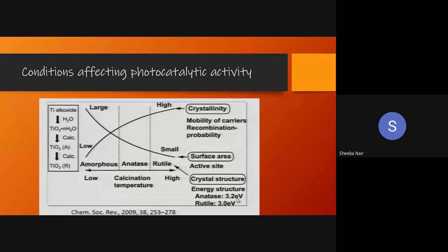Okay, what happens to crystallinity? The crystallinity improves, is high when you go from the lower to higher calcination temperature, whereas your surface area decreases from large to small. So how do you select a photocatalyst material? We want a better crystallinity and a better surface area for a photocatalyst, so you will have to select in this region. If you select a rutile one, you will have a better crystallinity, but a small surface area. Whereas if you select an amorphous material, you will have a better surface area, but a low crystallinity, which is undesirable again. So you will mostly select the anatase phase of TiO2 because it has a better crystallinity and better surface area.